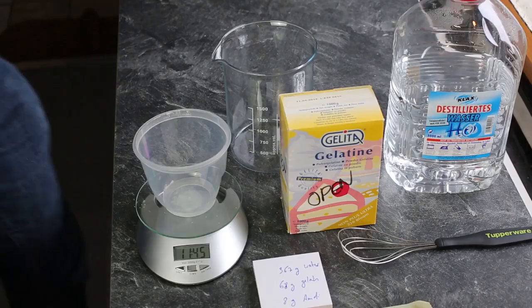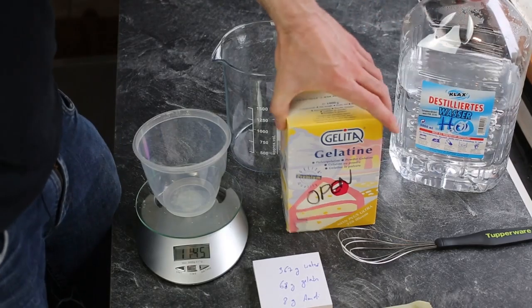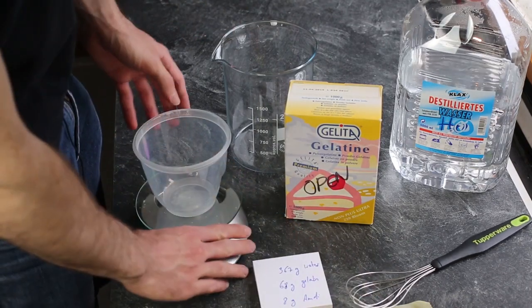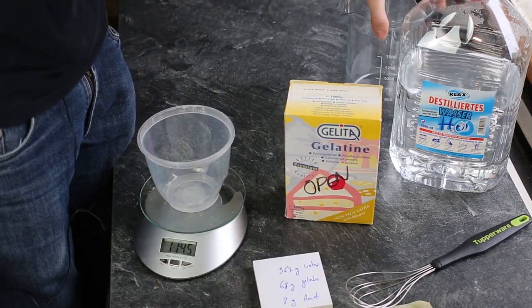This is how I mix the gelatin that I will use to coat the glass. My formula today is 367 grams of water, 68 grams of gelatin, and 8 grams of ammonium dichromate. This is a lot of dichromate in gelatin and will yield a rather thick emulsion. This recipe is optimized for using a low-power green laser.